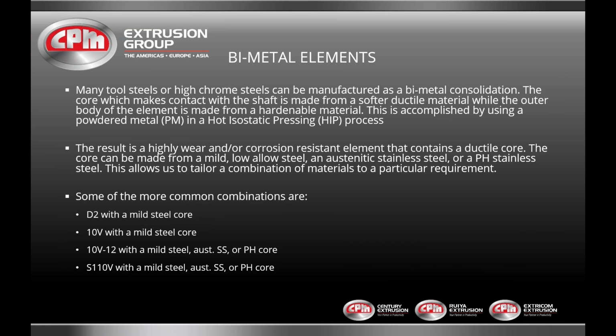The bimetal elements, many of which are tool steels or high chrome steels, can be manufactured as a bimetal consolidation. The core, or the part of the consolidation that makes contact with the shaft, is made from a softer ductile steel, while the outer body or part that contacts your product is made from a hardenable material. This is accomplished by using a powdered metal in a hot isostatic pressing process, or HIP. The result is a very wear and corrosion resistant element that contains a ductile inner core.